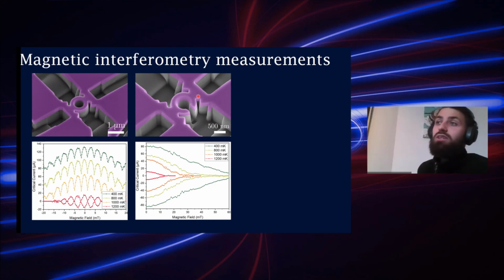Yes, we did carry the ring experiment out on thicknesses between—well, one sample was indeed 100 to 200 nanometers thick, and actually before I started my PhD, Kaveh Lahabi, who's also here in the audience, microstructured bigger crystal flakes that were up to a couple of microns thick even, and the SQUID oscillations still persisted.